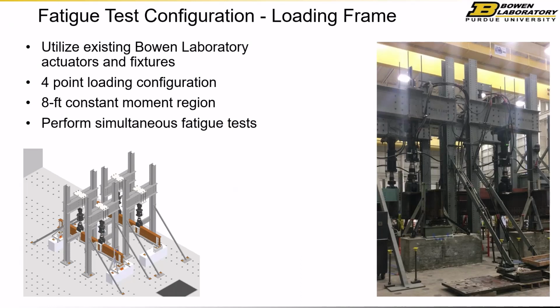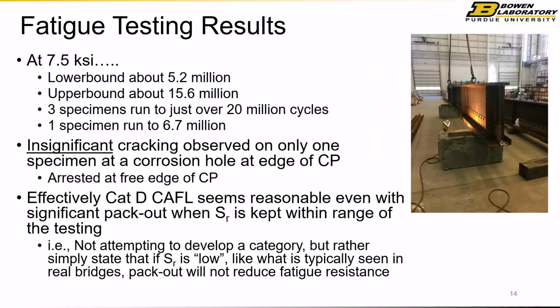In terms of loading for fatigue, we have a couple of large setups at the lab at Bowen Laboratory to allow us to run multiple fatigue tests at a time. So we are running twin fatigue tests side by side to try to go as fast as we could to collect the data. And some tests were done in strength for compression members, but for fatigue, these setups work out really nice. And so we have an 8-foot constant moment region or zero shear, right? And so that gives us a nice uniform stress range over a significant length of rivets and where the damage is. And then we have a shear span portion also where we have a fair amount of damage and stress range, but also a good amount of shear.